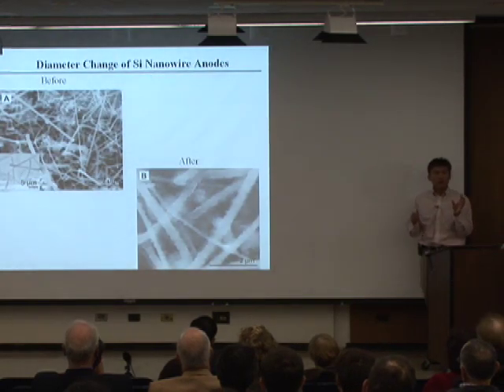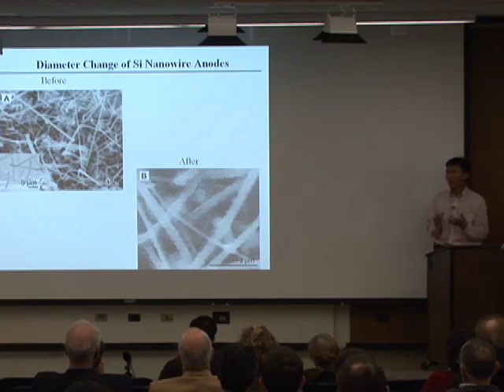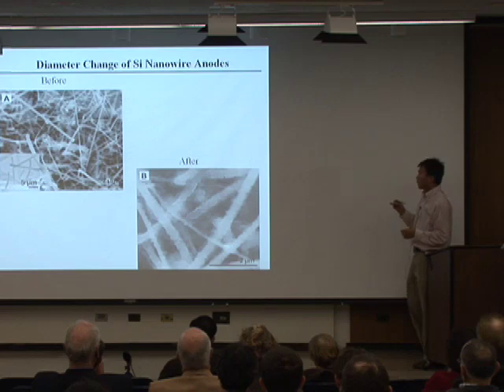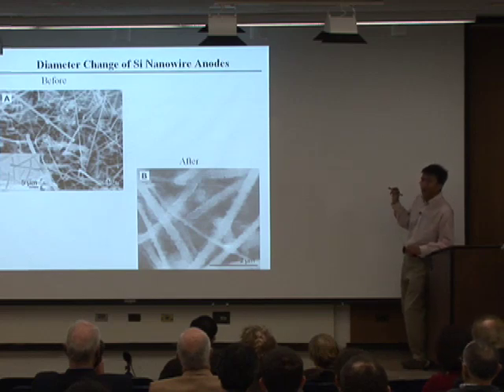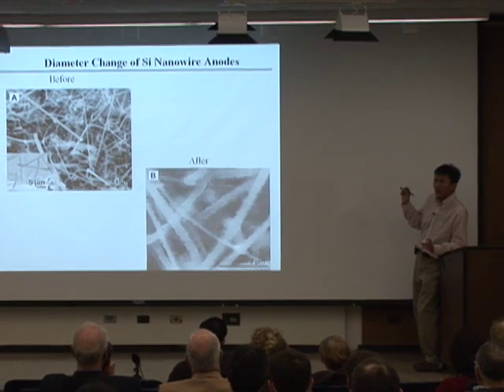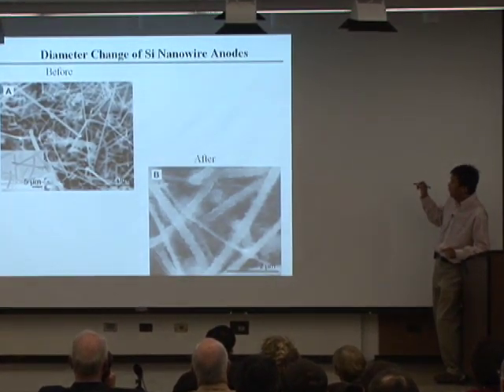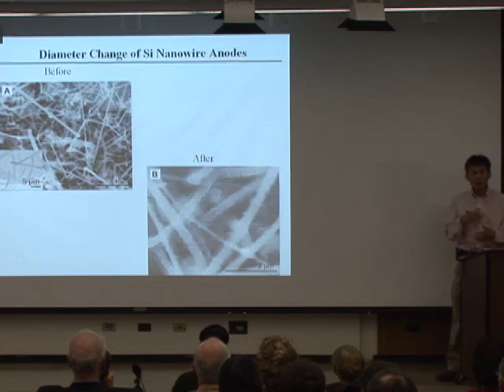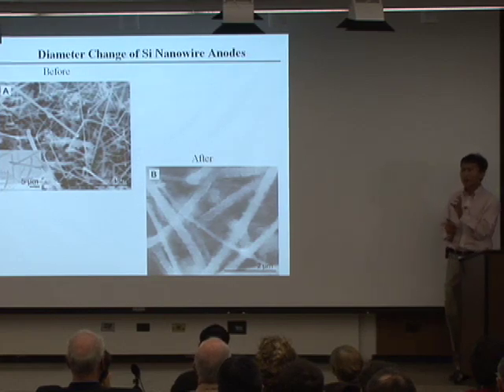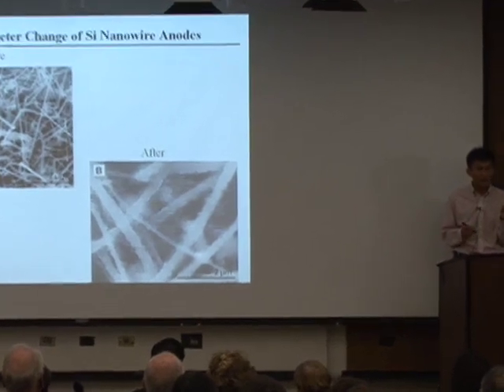So what about the breaking problem? Breaking has been the biggest problem for silicon. After we do battery charging, we look at how the nanowires look under a scanning electron microscope. This is before lithium coming in. This is after multiple times of charging and discharging. One piece of information you get is that the nanowires don't break. They still look like nanowires. And the second thing is their diameter becomes bigger. They become fatter, but they still don't break. So that's good news. This is consistent with what we are thinking.